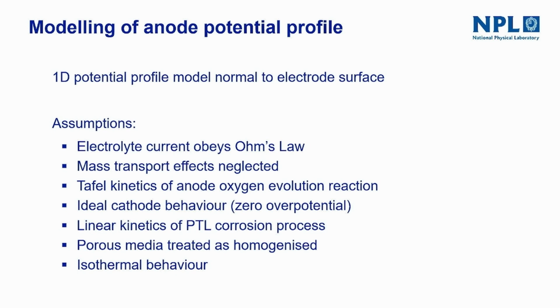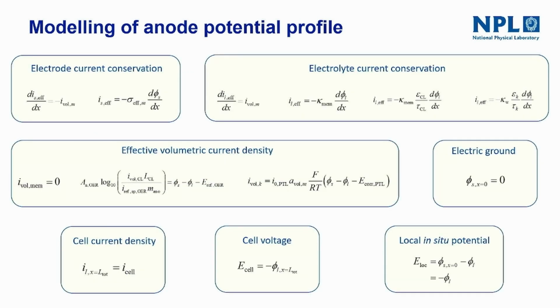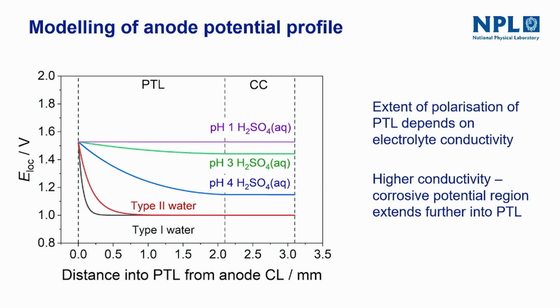We then also developed a 1D electrochemical model of the anode potential profile, so from the full 2 volts at the electrode down to the 1 volt open circuit potential of the platinum in oxygen. I won't go through the details, but this is just to show that there is a real model behind these curves that I'm going to show you. You can read the paper in your own time. So this is the model, and these are the 2 plots that are most relevant to service.